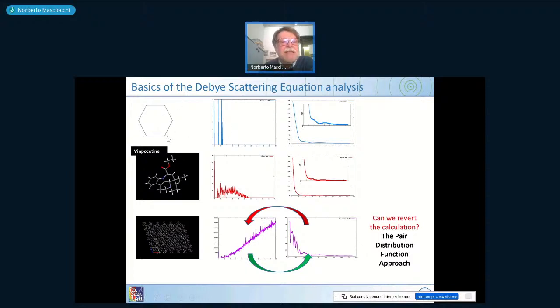Originally, you have 6 atoms times 6 minus 1 times 5 divided by 2. Again, we have 30 distances, which are counted twice because one atom sees each other also in a reverse manner. These 15 distances are then fed to a computational system and give you exactly what you've seen before. So the plot we've seen before was computed from the histogram of distances which you compute from a small model.